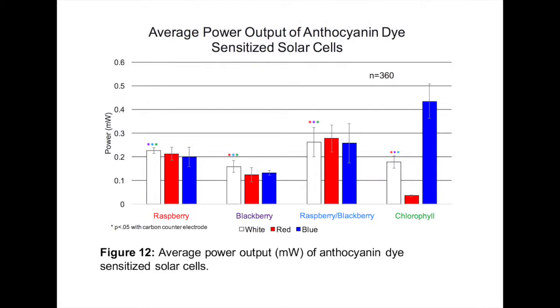Before we looked at studying quantum dots, anthocyanin dyes were used in conjunction with a carbon counterelectrode to test that co-adsorption is more efficient than having individually deposited dyes. Under white light, the raspberry-blackberry combination produced the most power at 0.26 milliwatts, proving that co-adsorption of dyes can be used to increase efficiency.